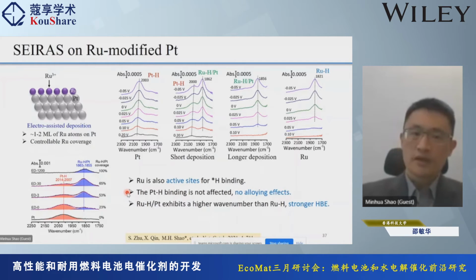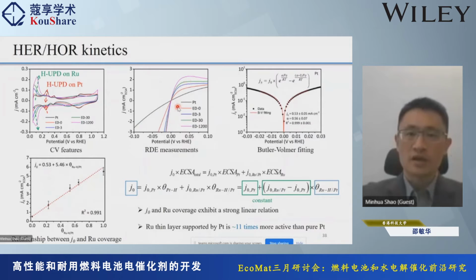Then we also measured the hydrogen oxidation reaction kinetics, and also HER, using the Butler-Volmer equation to fit the exchange current. And we found that this exchange current has a linear relationship with the ruthenium coverage. So that means ruthenium is actually the active site, instead of playing the role of providing the adsorption site for oxygen. So this is not the bifunctional mechanism. Instead, ruthenium is the real active site in this system.